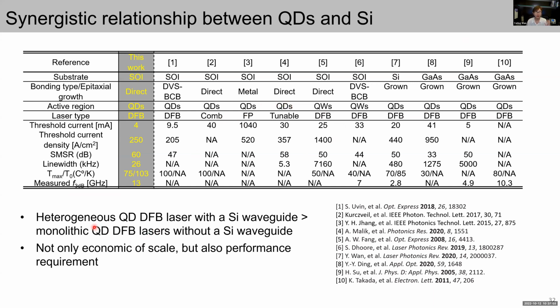So what we want to emphasize is that the heterogeneous quantum dot DFB laser with a silicon waveguide can significantly outperform monolithic quantum dot DFB lasers without a silicon waveguide in terms of linewidth, bandwidth, side-mode suppression ratio, etc., which we are very excited about, as it shows a synergistic relation between the unique capabilities of III-V quantum dots and silicon, allowing for not only a reduced cost due to the economy of scale, but also much better device performance, exceeding what can be achieved with purely III-V quantum dot devices, which means when you put lasers on silicon, you not only get a better substrate, you actually get better lasers.